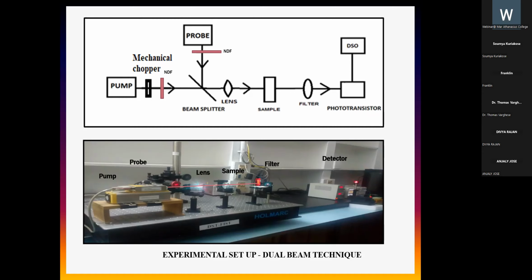We have used a DPSS continuous wave laser of 488 nanometer with maximum power of 50 milliwatt as the pump for the generation of thermal lens. And the detection was done using a helium neon laser, which is of 632.8 nanometer, for detecting the output. Required neutral density filters were used to lower the power of both pump and probe to avoid spherical aberrations due to the interference in the transmitted beam at high powers.